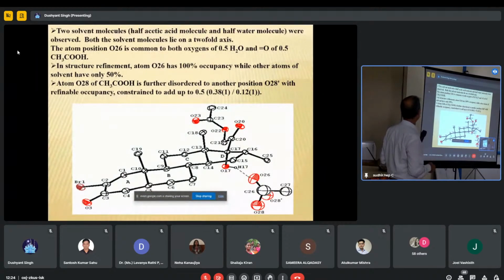Now you can see here, this is a very interesting molecule I have solved. It is a steroidal molecule I have taken. 2 solvent molecules, because this is acetic acid. When I solved all the molecules of acetic acid, they were showing 50% occupancy, 0.5. This molecule is showing 100% occupancy. But 1 oxygen of the acetic acid solvent is showing 1 occupancy. So it is very, very difficult to resolve it.